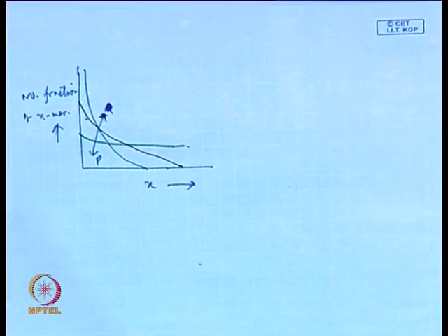So, at any conversion region, whether it is low conversion, medium conversion or high conversion, the reaction medium will have, in number fraction, in number, not the weight, the maximum number of monomers present. Now, the number of monomers will decrease as the conversion goes up, but even at very high conversion there are a significant number of monomers present in the reaction.